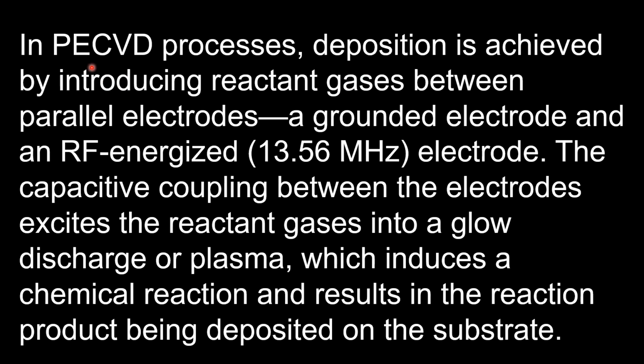In the plasma enhanced chemical vapor deposition process, the deposition is achieved by introducing reactant gases between parallel electrodes. One electrode is a grounded electrode, whereas the second electrode, which is the top electrode in the plasma enhanced chemical vapor deposition system, is known as the RF energized electrode. This RF energized electrode is operated at high frequency and high voltage. The RF energized electrode operates at radio frequency, which is 13.56 megahertz.